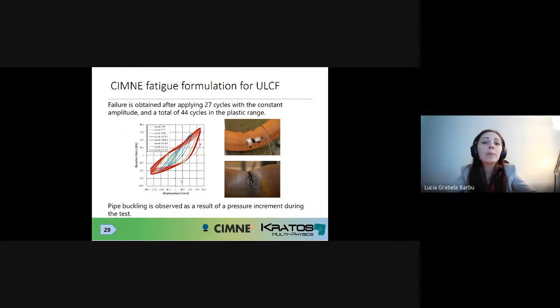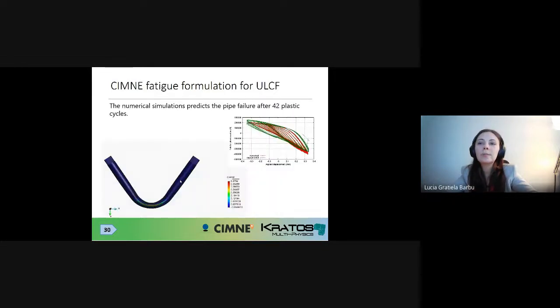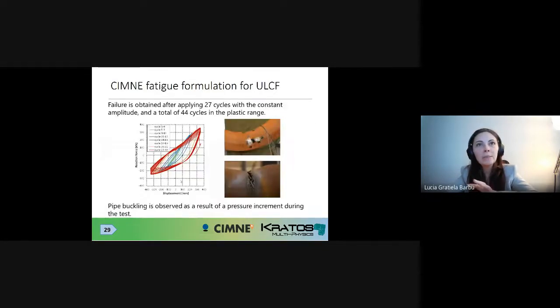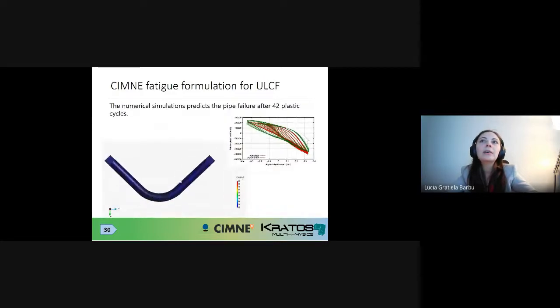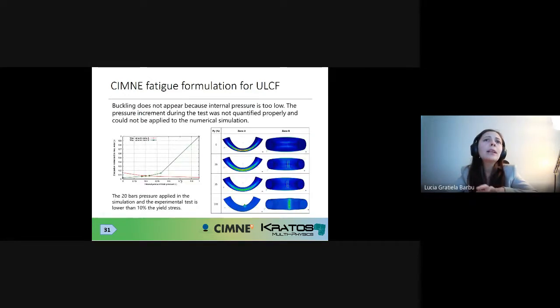Okay, now results regarding this. We used it for a project in oil and gas for the piping industry. And here you can see, for instance, an elbow which was subjected to cyclic loading with some internal pressure. And you can see the adjustment between the numerical and the experimental behavior, which was quite good. However, regarding the failure mode, there was a slight difference because of the level of internal pressure. And this motivated us to do a whole analysis of how the failure mode changed with the level of internal pressure.